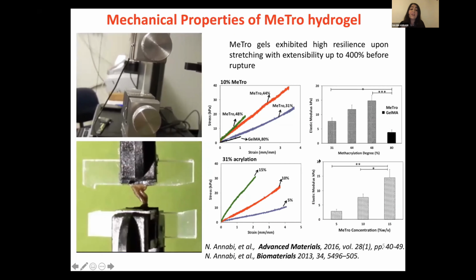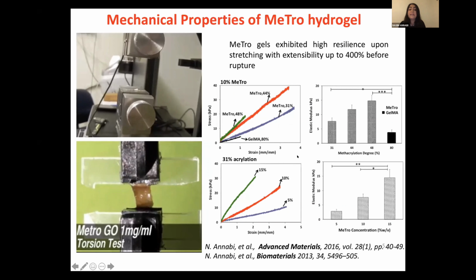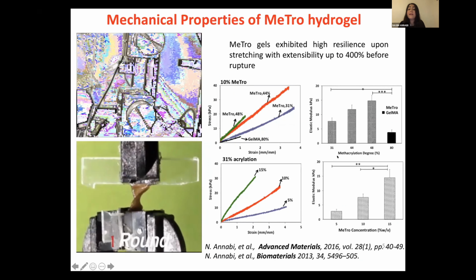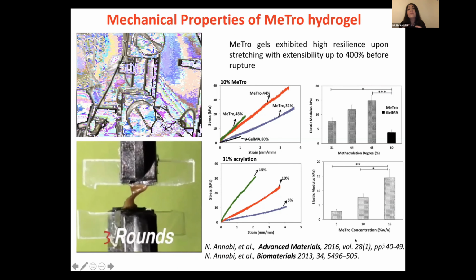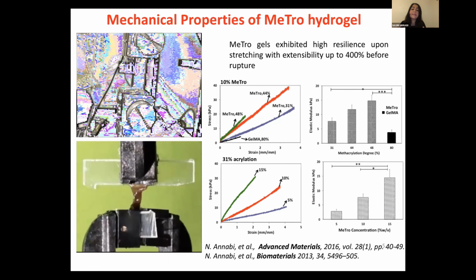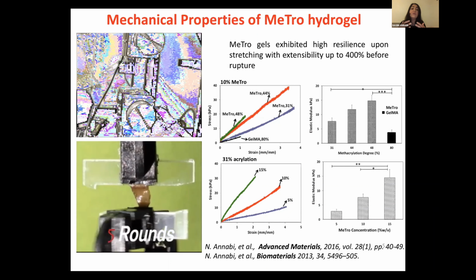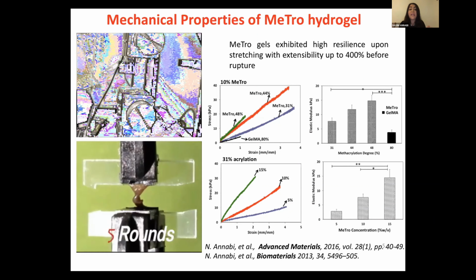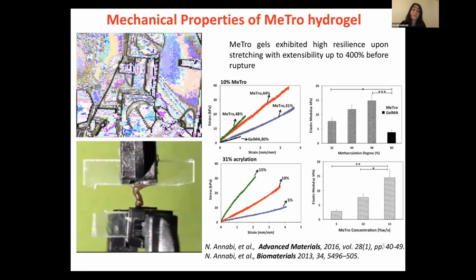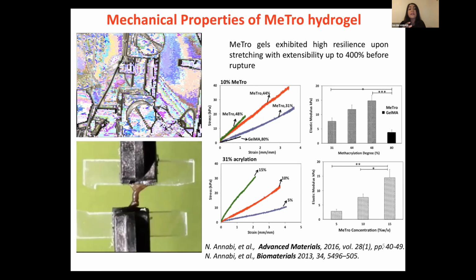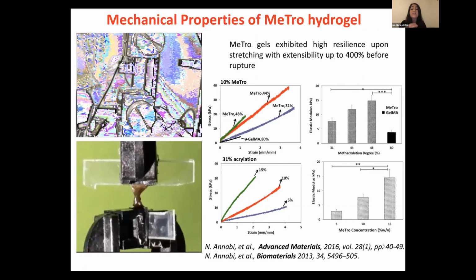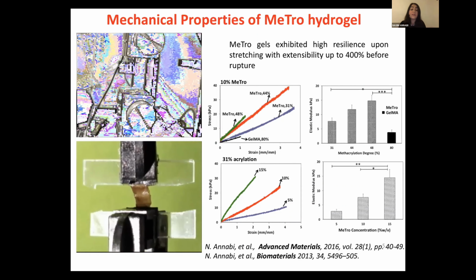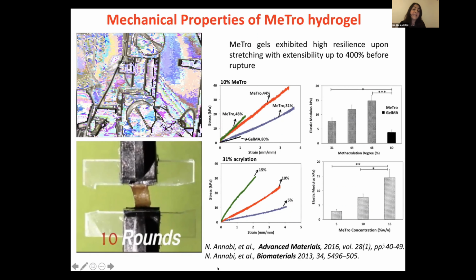And with these panels of data based on tensile tests, we show that the properties of the Metro are tunable, basically by changing the degree of functionalization or by changing the concentration of the protein that you use to form these scaffolds. You can tune the properties. And this opened lots of avenues for us to use Metro for different applications, because we can not only tune the mechanical properties of this biopolymer, we can also control other properties, right? Degradation rate, swelling, and even biological properties of the Metro when we interface it to different tissues for different regeneration